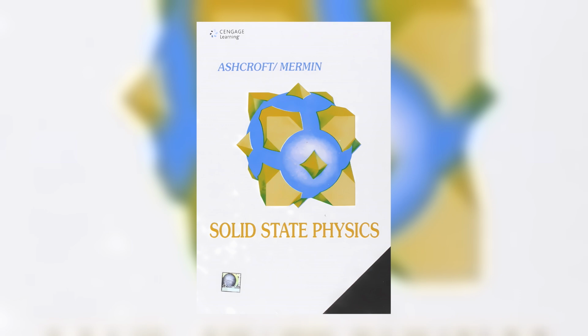This section explains why the interaction that orders spins in a ferromagnet is not really magnetic at all. Call the interaction magnetic, and you have already misread it. The moment-to-moment coupling that aligns spins in a ferromagnet is electrostatic, ordinary Coulomb repulsion wearing spin's clothes. The dipole fields are 1,000-fold too weak. The ferromagnetic transition sits at hundreds of Kelvin, not the few Kelvin that dipoles could enforce.